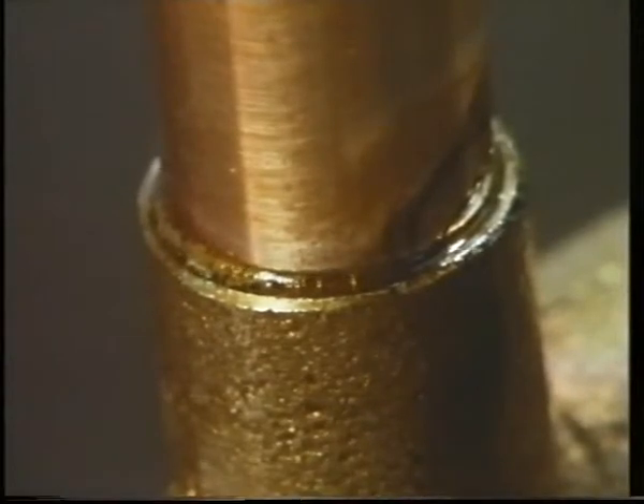Let's look at a cross-section through part of the soldered joint. Here it's magnified nearly 300 times. The band in the middle is the solder, the top and bottom, the two pieces of copper being joined. Now, wherever the solder comes into contact with the two copper surfaces, a very thin layer of alloy is formed. It's an alloy of tin from the solder and the copper being joined.